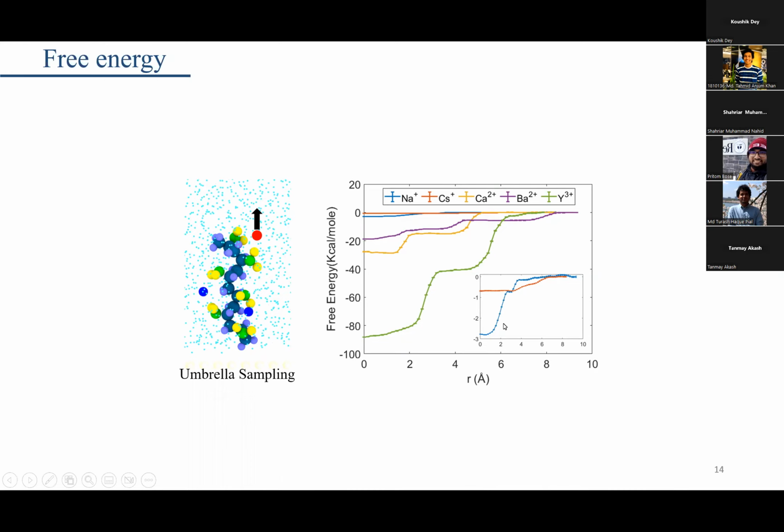And in another way, cesium is very large, so its solvation shell is very large. If your brush height is shrinking even a little, it can expel more cesium from the brush layer. Because when cesium tries to go into the brush layer, it will bring all the water in its solvation shell with it. So it will have a very large energy penalty if it tries to go inside the brush layer. Because inside the brush layer, the cesium will be very stable and won't move. And when things don't move, their entropy reduces a lot. So it's very unfavorable for cesium or a highly charged ion to go and stay inside the brush layer compared to a smaller ion. Lots of things are contributing, it's a very intricate system.